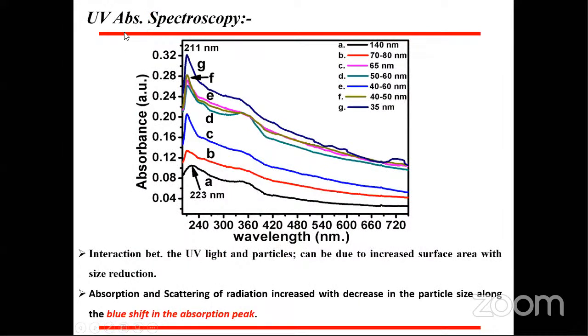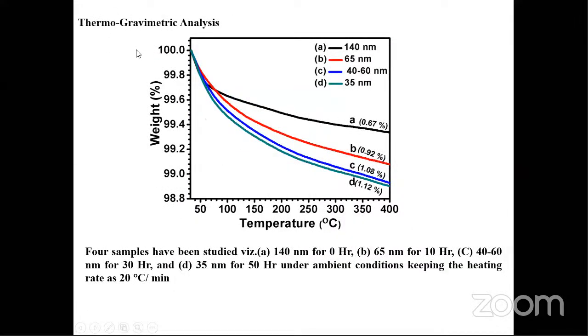We also observed the absorption behavior using UV absorption spectroscopy. The interaction between UV light and particles can be due to the increased surface area with size reduction, and a blue shift was obtained when size reduction happened. We also did thermogravimetric analysis and observed some weight loss. The 0-hour sample shows 0.67% weight loss, and the 35 nanometer sample, which is the 50-hour ball milled sample, shows 1.12% weight loss.